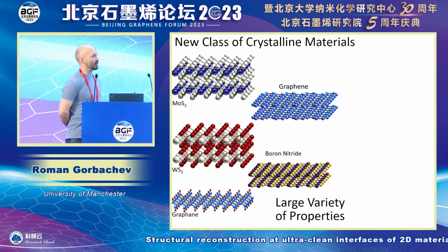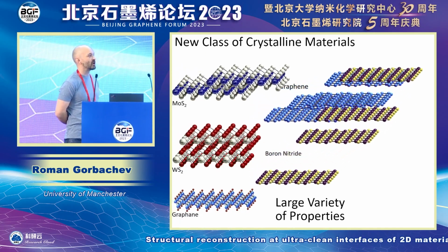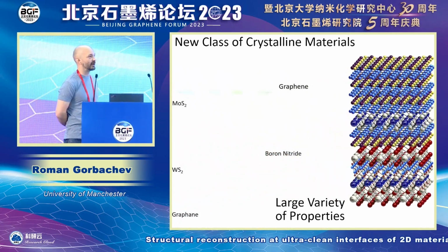The key for the 2D materials is that we can really mix and match different layers, and we can produce these layered heterostructures without really caring whether they like to grow on top of each other or not. Because there's a mechanical transfer and we grow them separately or exfoliate them separately, we don't need to worry about the chemical matching and matching of the chemical conditions. And that really opened a huge field, which is blooming and expanding even now, so many years later.